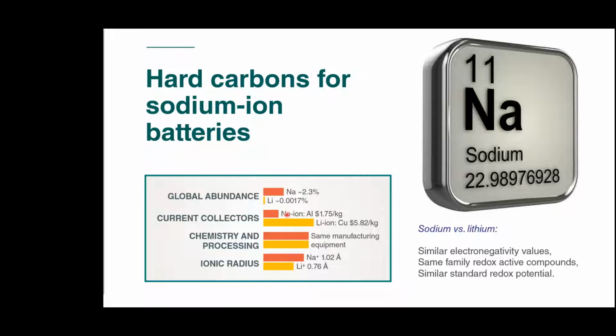So we use a method in the group called hydrothermal carbonization to create hard carbons from biomass. And this is a really valuable tool because we can take something that's otherwise a waste material and turn it into something valuable. So we can start with any biomass precursor, but at its simplest, we take a sugar molecule like glucose, and we hydrothermally synthesize this at a relatively low temperature, and under self-generated pressure, we form some carbon spheres, which we can then pyrolyze to obtain a conductive carbon material, which we can then use in the battery. So it's a really nice versatile technique because we can tune the porosity and morphology very easily on these carbons by just varying the synthesis conditions and the precursor.